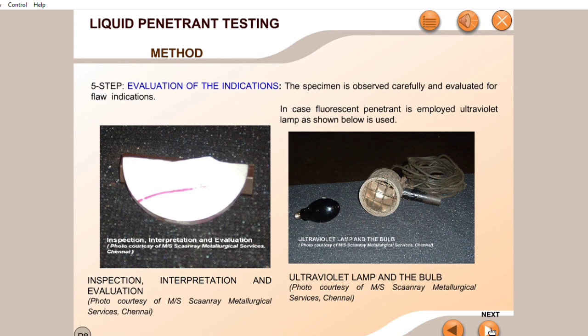If you perform the fluorescent penetrant, then the light intensity of the ultraviolet light must be greater than 1000 microwatt per centimeter square. And if we are talking about the sensitivity of fluorescent penetrant and of visual penetrant, fluorescent penetrant has the higher sensitivity. You can find minor indications much more in the fluorescent type.